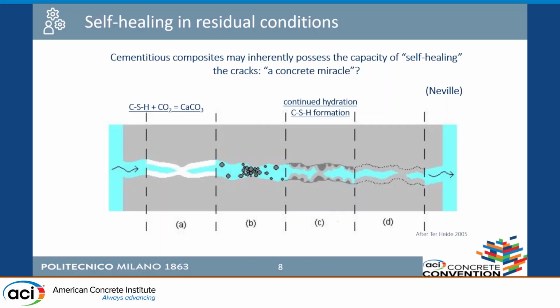Self-healing is a phenomenon taking place especially in the cracks, thanks to the formation of calcium carbonate, which you see here on the top left, and also the continuous rehydration of anhydrated cement particles. Because you know that in HPC and UHPC, we have a lot of binder that is not hydrated. And so during heating sometimes, and this explains the gain of strength between 200 and 300 degrees C. And then in the residual phase, with the passing of the days, we have the hydration of these particles, and so we have a recovery of the material properties.